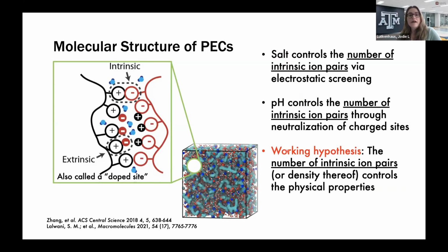So of course, pH can have a major role. Our general theme in our group is that changing the concentration of intrinsic ion pairing is going to adjust all of the physical properties that you'll see macroscopically. To understand that, it requires us to form a way to count the intrinsic ion pairs and the extrinsic ion pairs, and then correlate that count to physical properties like the glass transition or the dynamic mechanical relaxation.